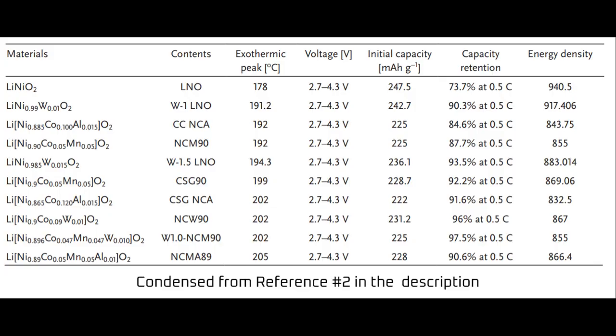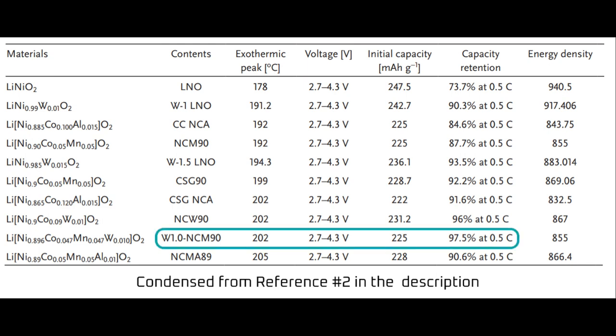Let's go back to our table and see if we can find a tungsten-based heterostructure cathode that also contains manganese or aluminum and see how it performed. I've highlighted here an NCM90 cathode that's been doped with 1% tungsten. It has good thermal stability and has roughly the same specific capacity as Tesla's current cathode material. If we look at the capacity retention at 100 cycles, it thrashes the NCMA-89,